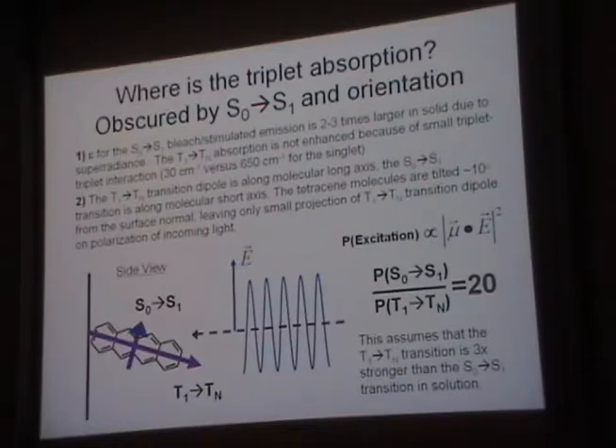And this was mentioned, but not quantitatively described in an earlier paper. We sort of quantitated it, and it's a big, big effect. And a factor of 20 even without the superradiant enhancements with normal incidence, right? So just from the orientation of the crystallites, right? They're not randomly oriented. If they were, this would be an easier experiment, but they're typically not randomly oriented on the substrate. The triplet has the bad orientation to interact with the light's polarization, and it appears up to 20 times smaller than the singlet. And this is not even taking into account the fact that the singlet's bigger because it's got this superradiant enhancement. Okay, so once you're talking about a factor of 20, you can miss that in the signal-to-noise of your transient